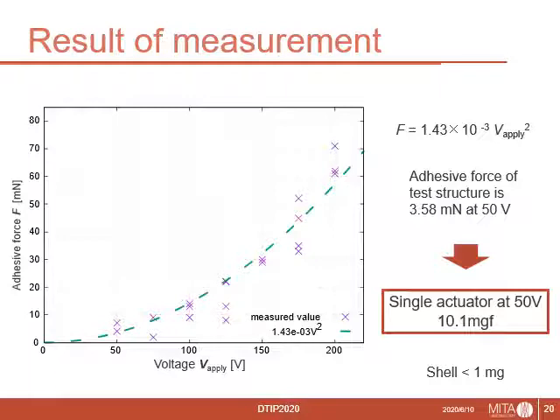This is the result of the adhesive strength measurement. The data is fitted by the second-order polynomial, 1.43 times 10 to the minus third V squared. From the fitting curve, we estimated test structure's adhesive force was 3.58 millinewtons at 50 volts. Therefore, a single actuator operated at 50 volts can suspend 10.1 milligram weight. This value is sufficiently large to suspend the micro-robot shell.